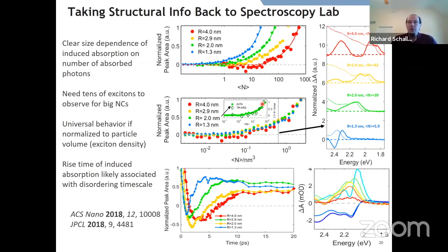And we generically would expect from thermodynamics, because I said that the melting point gets lower for smaller nanoparticles, you wouldn't expect them all to necessarily fall on top of each other. So the fact that they do overlap is suggestive of this being a non-equilibrium phenomenon, that you're seeing lots of disordering of these crystalline lattices, but it's not truly a phase transition in that sense, because that you'd expect to be taking place at lower fluence or lower ultimate temperatures of the lattice, whereas when they have the same density of excitations, you expect about the same temperature.